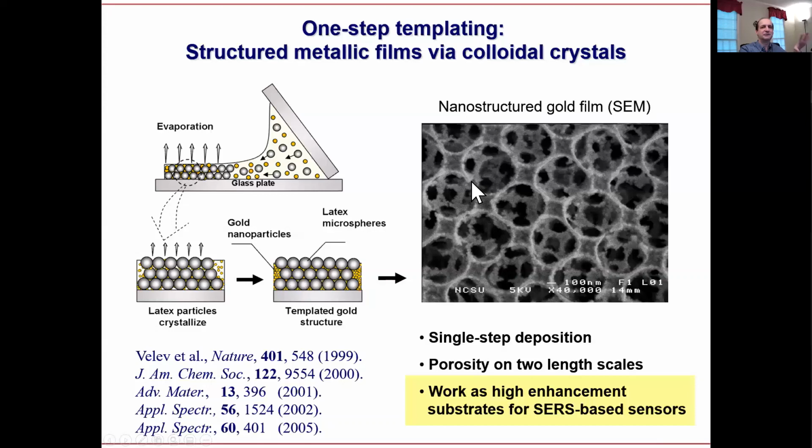Okay. So this is how you make it. You can say, oh, but I can make a very thin layer of gold by metal deposition, right? You can do that, but then you're not going to have the high surface area. You're going to have a layer of gold. Even if, people have been doing this through latex or silica templates, you can deposit gold here, but then you're going to have a very thin layer of gold that doesn't have this high surface area, which is very useful in this case, right? It makes very strong plasmons. So this is one application.